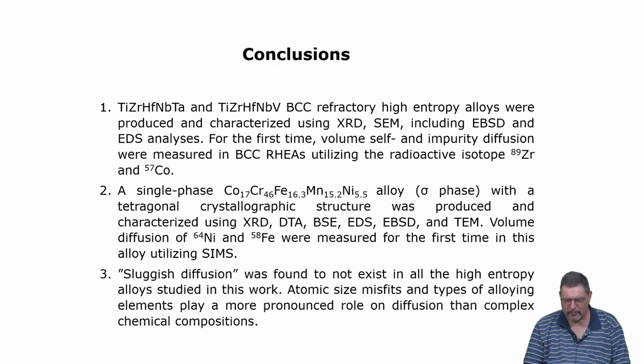So refractory BCC high entropy alloys are high entropy alloys in the true sense, so they can form complete solid solutions. Also, this is true for the sigma phase. Sluggish diffusion was found not really to exist in all the high entropy alloys studied so far. And it seems that atomic size misfits and the type of alloying elements play a more pronounced role than having a complex composition. However, there is not yet an established pattern, so we cannot say a priori we take these elements and we have this type of lattice mismatch, this type of mixing enthalpies, and we would expect this type of diffusion behavior.